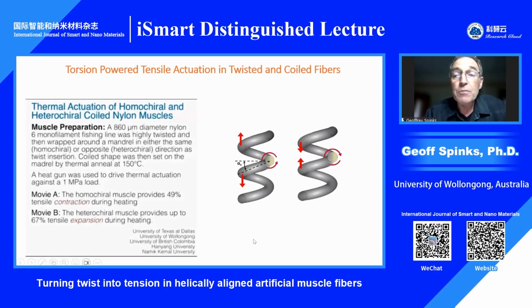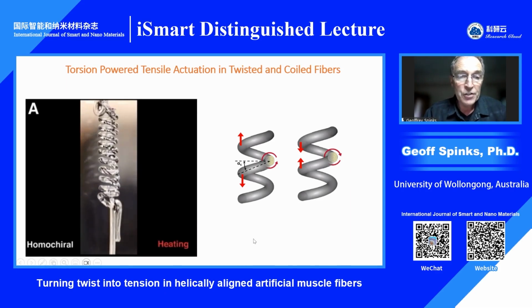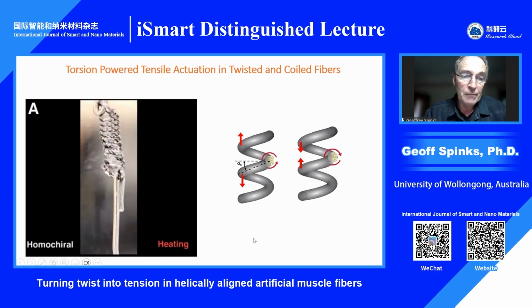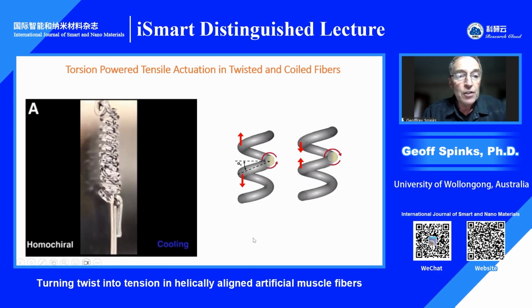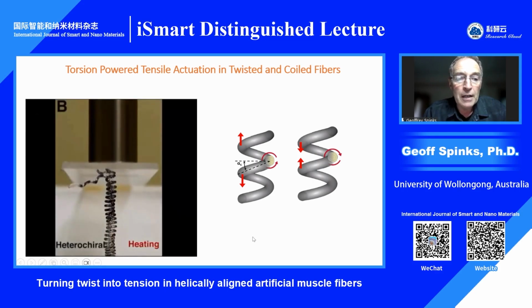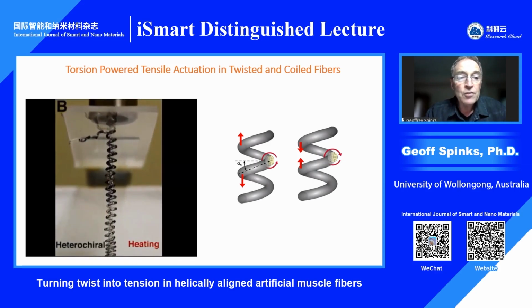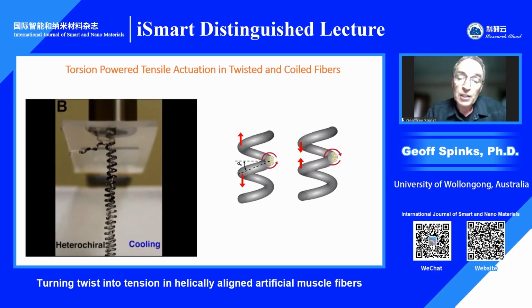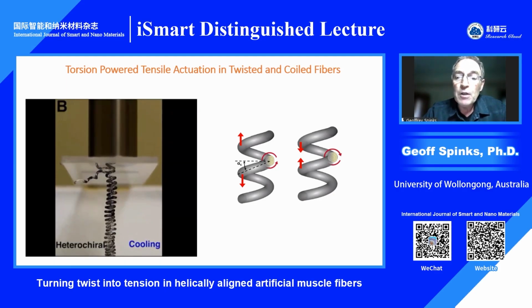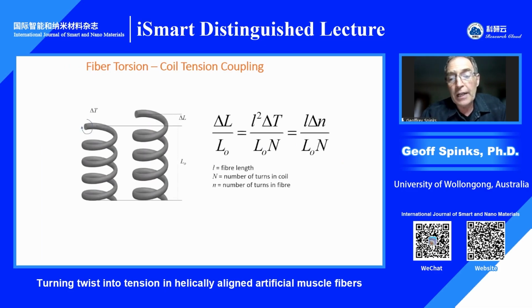And here are the experimental results. This is the homochiral. You can see when it's heated, it contracts in length, and when it's cooled, it expands. So now the twist direction and the coiling direction are the same. Next, if we take the same fibre and make it into a coil of the opposite hand, you can see on heating now it expands, and on cooling it contracts. So this is telling us, as the image on the right is showing, that the twist occurring in the fibre is actually what's driving the coil length change. If the twist turns one way, the coil length will contract. If it turns the other way, the coil length will expand. And in fact, this is not a new discovery.